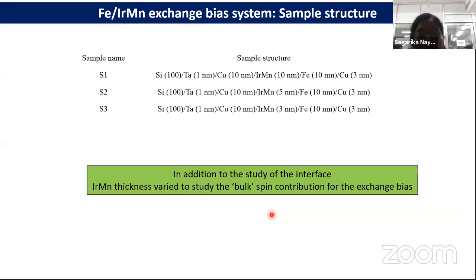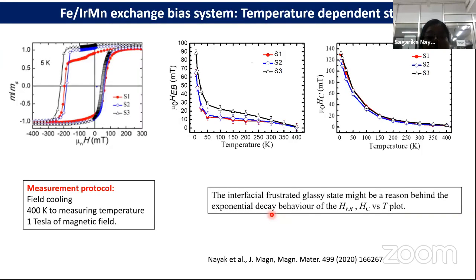And also in this study, we varied the thickness of iridium manganese from 3 to 10 nanometer to study the role of bulk of the antiferromagnet on exchange bias properties, whereas the ferromagnet iron layer thickness is kept fixed. Now I will move towards the result section.